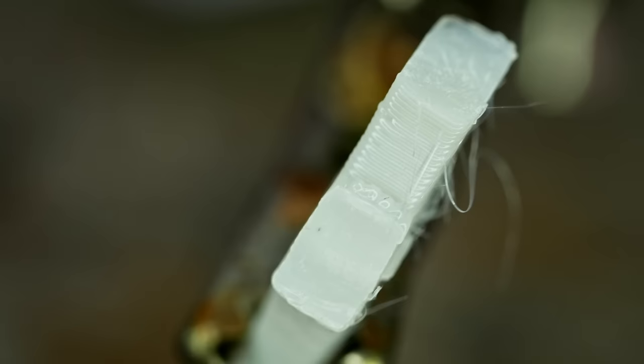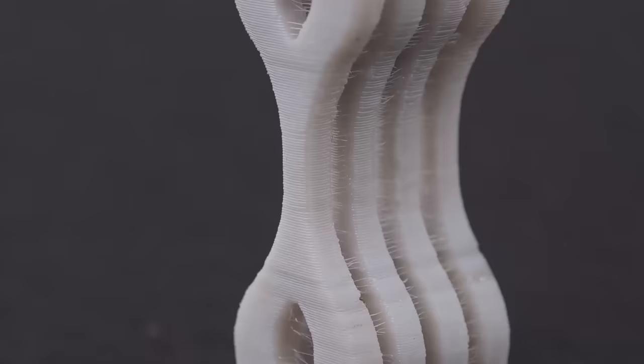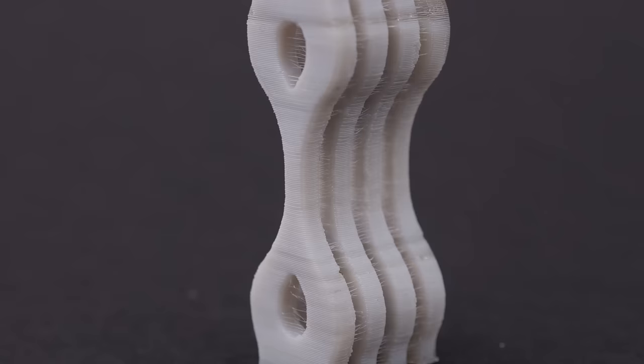If we take a look at the rupture surface, one side even looks as if it was injection molded, because there aren't any layers or voids visible. Of course, the parts crystallized out, so it would probably be different on a normal part, but still impressive results.